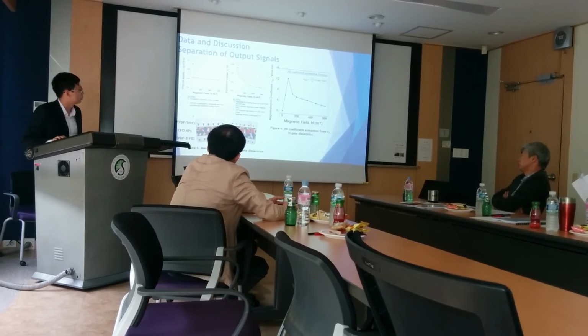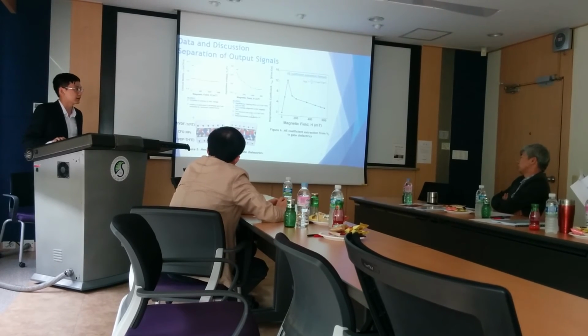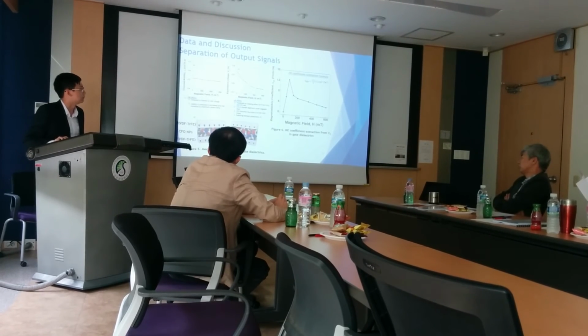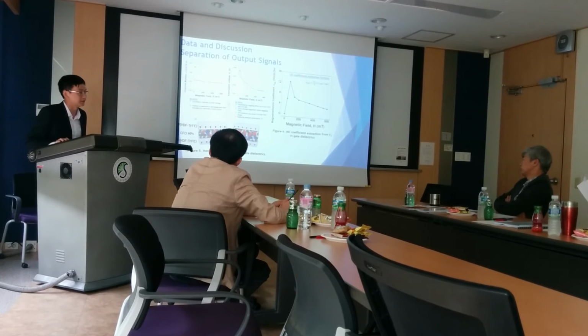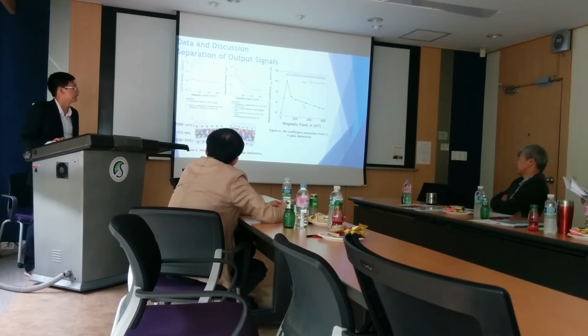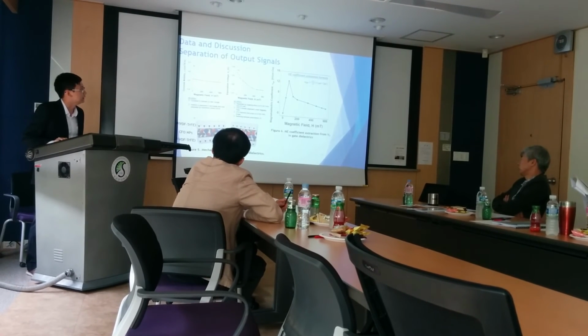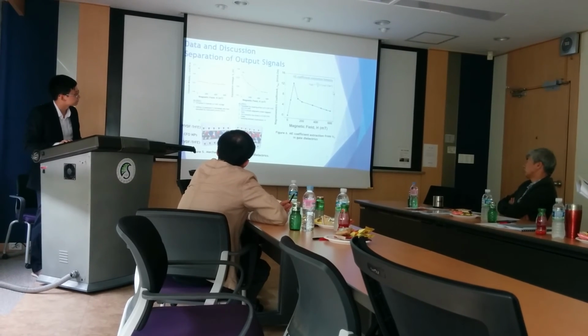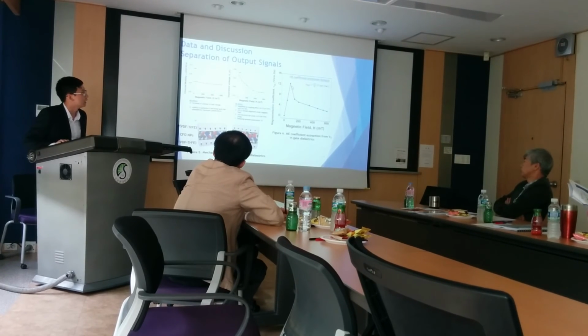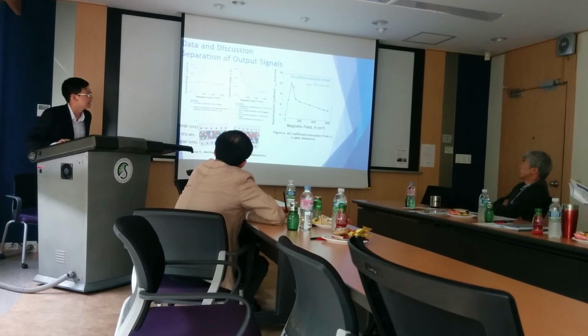So, as in figure 5, we found that when we apply the magnetic field, two effects are excited simultaneously. That means there are the magnetoresistive effect and the magnetoelectric effect. And continuing, we extract the magnetoelectric coefficient from the equivalent voltage D0 by the formula in figure 6, as you can see. In figure 6, the magnetoelectric coefficient increases up to the highest and then decreases up to 600 millitesla.